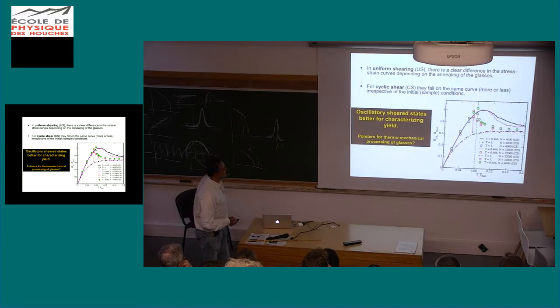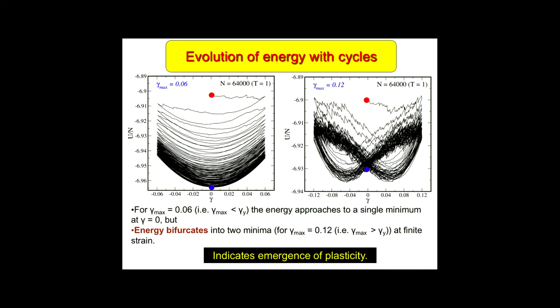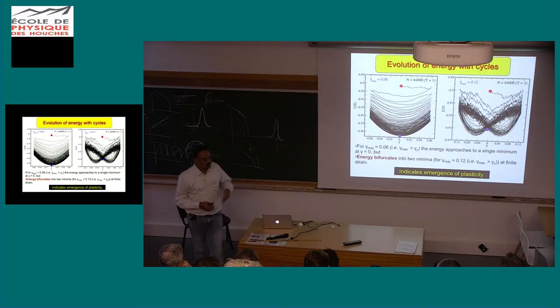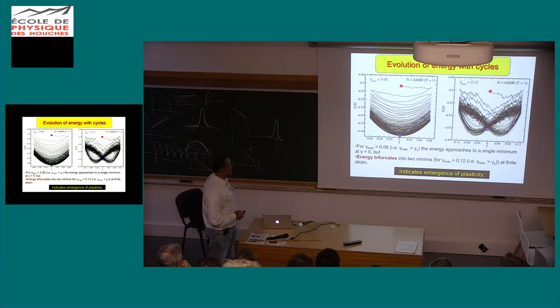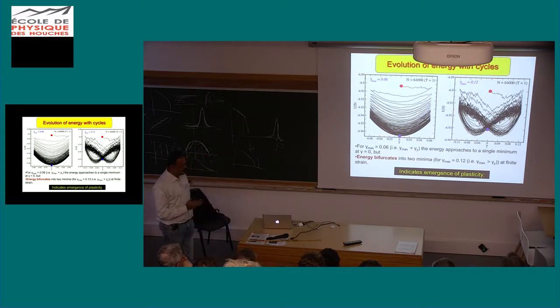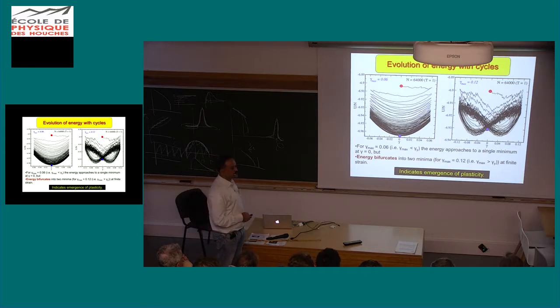Okay, so here is a summary of a lot of different cases which illustrate the same point. So if one looks at what's happening through the cycles and through the strain range in each cycle, one has a picture like this, where one starts out with a high energy, and through the different cycles one is at an amplitude below the yielding transition, annealing the glass to lower and lower energy values. But when the amplitude becomes bigger than the threshold amplitude, one has a very different picture, where these energy curves bifurcate into two lobes, where the strain at which the lowest energy is reached becomes finite rather than zero.